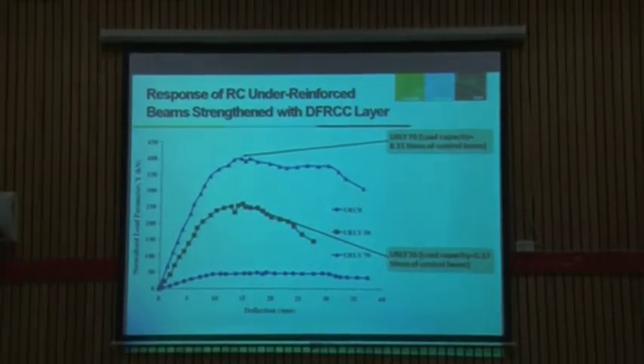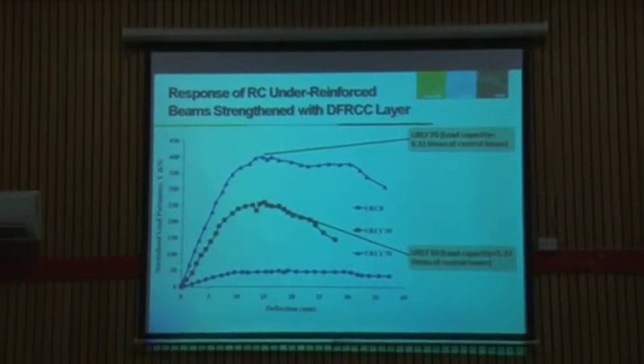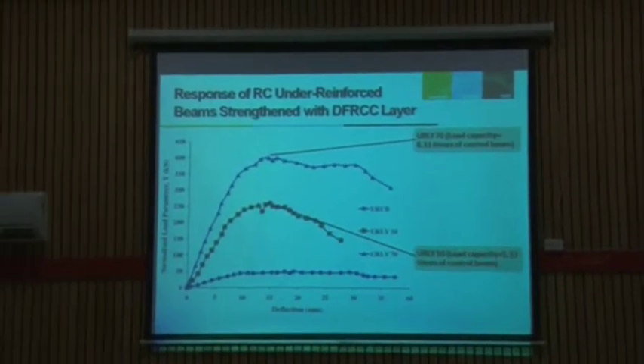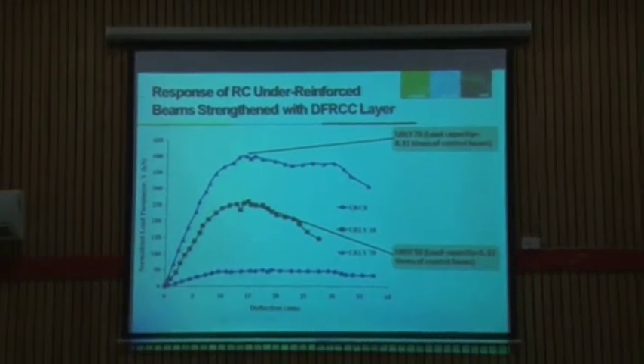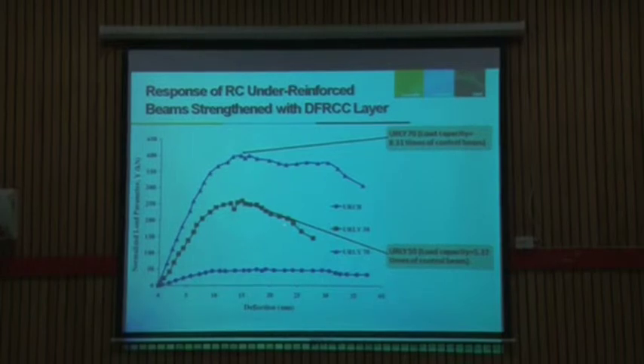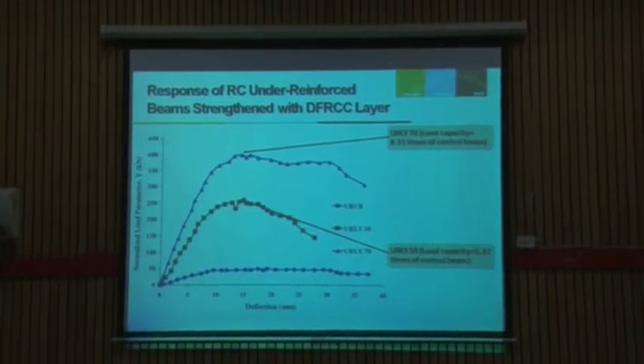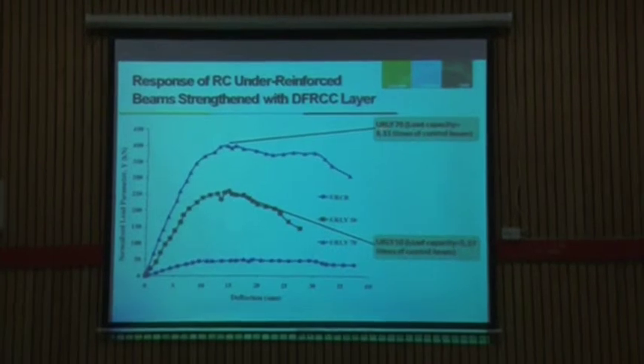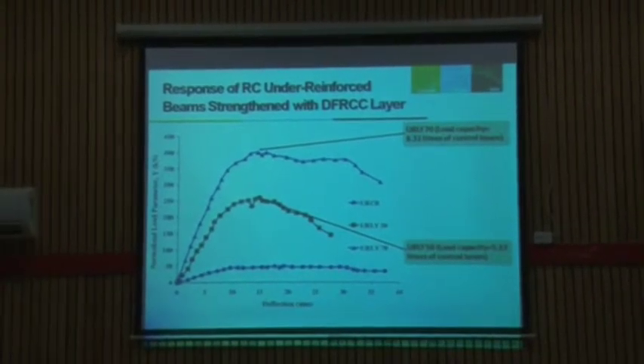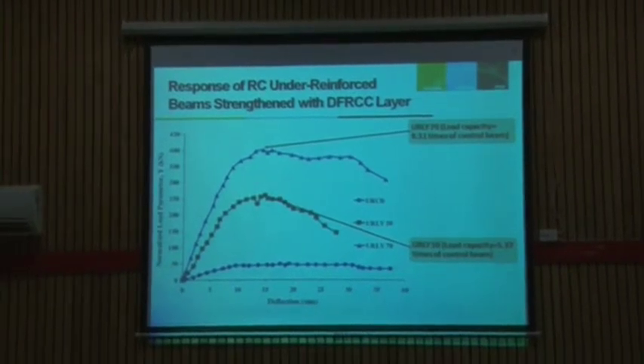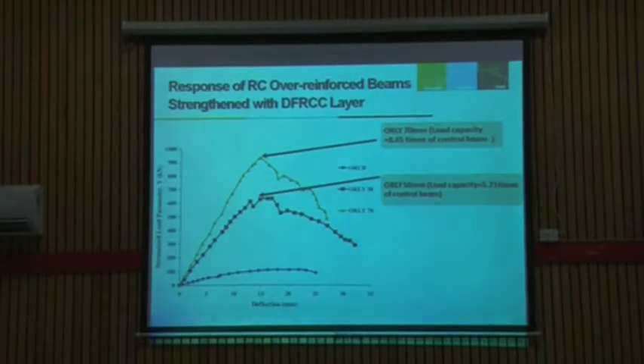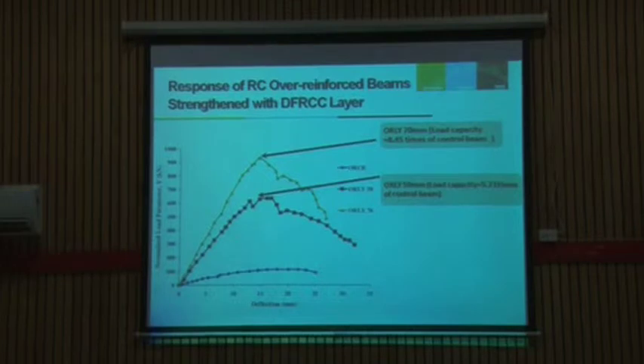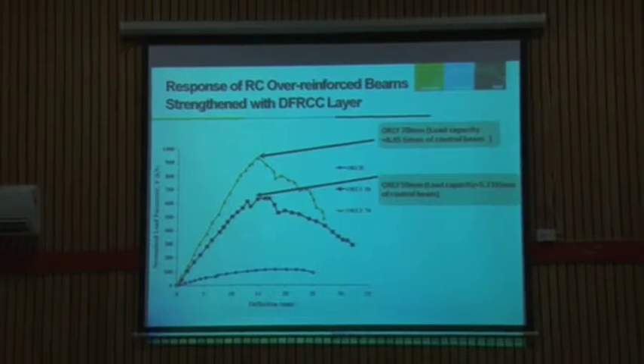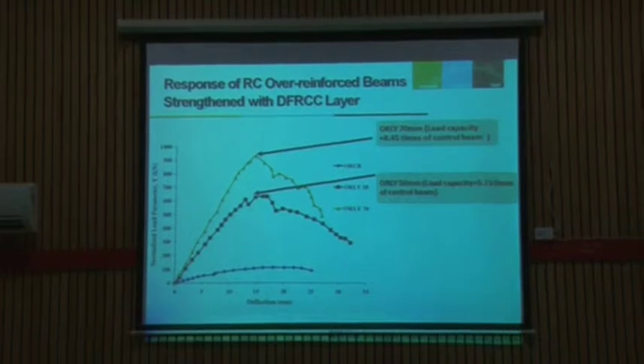Similarly, here going for the layers concept, external layers, we are using strips of ECC and putting them as external layers, and there also we are getting significant improvement. This is a control beam, and there we are looking at 50 and then 70 mm thickness of layer. You see that the strength improvement is about 8.31 times the control beam. There is significant improvement there, just for a 50 mm thickness of ECC layer. Similarly for over-reinforced beams, we are not getting that improvement advantage as in the case of under-reinforced beams, but still ductility is improved in the system, even for over-reinforced beams.